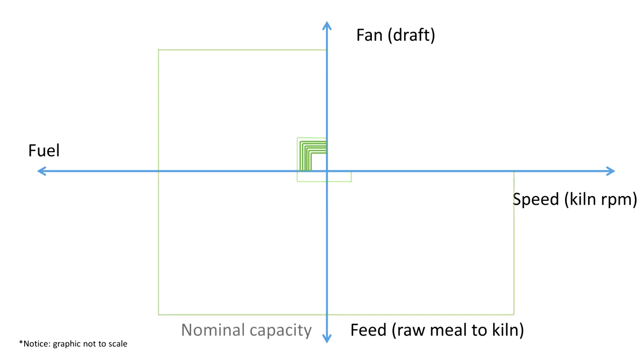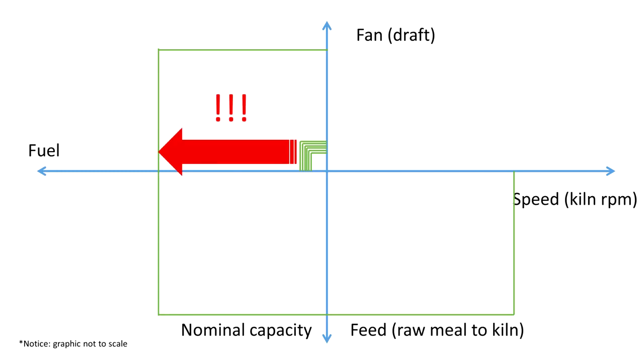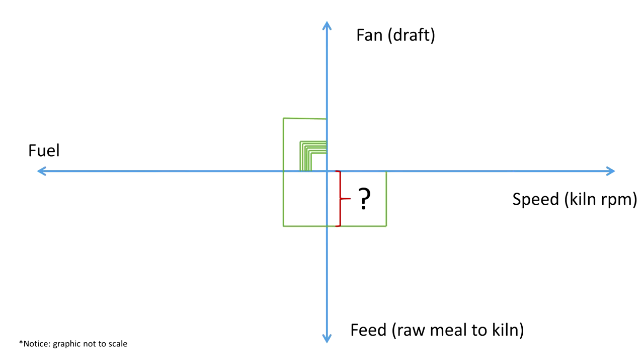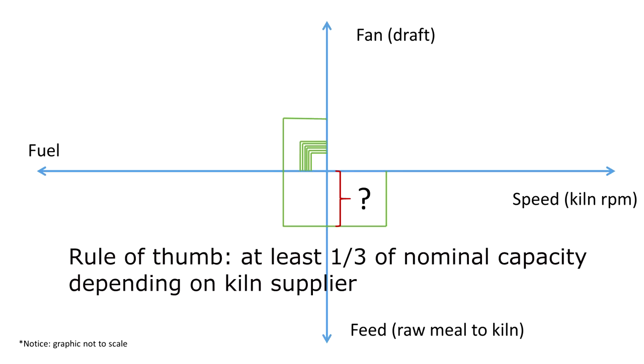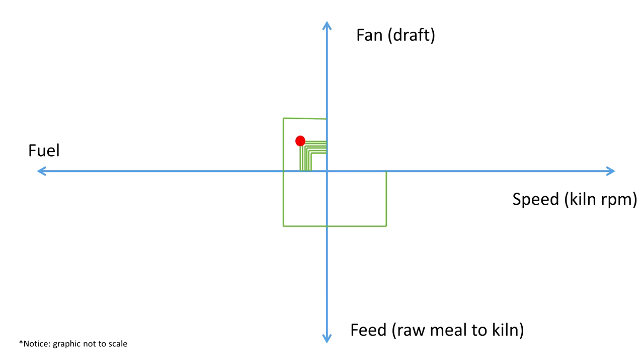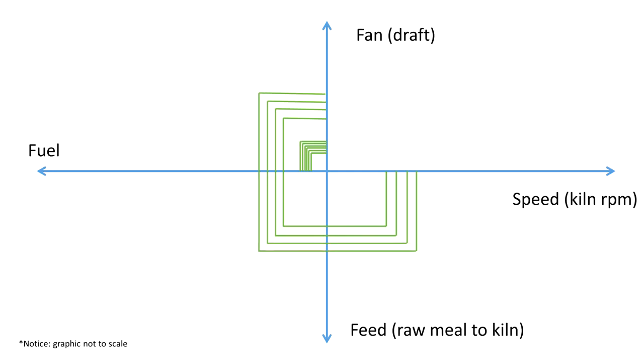The other extreme is to go directly at full capacity. This is very dangerous to expose my system to such a sudden increase in thermal load. Finally, what is considered an adequate first feed? The rule of thumb says it should be at least 1/3 of the nominal capacity. We start the fan, fuel, feed, speed, and keep on running this cycle till reaching full capacity.